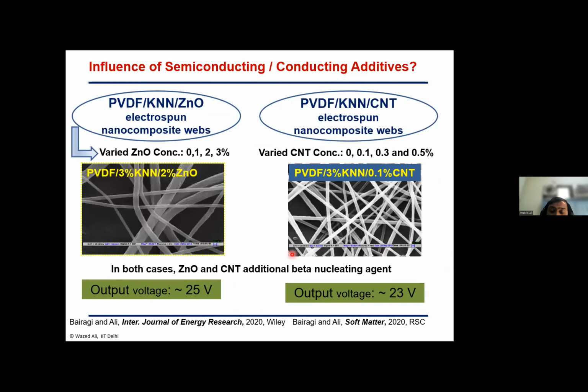And another concept has also been conceptualized over here. For example, if there is a charge which is going to be produced in the structure, that charge has to flow, right? Flow on the surface, so that by application of some electrode on the top and bottom, we can harvest the charge. So if we include some kind of semiconducting material or maybe some kind of conducting material within the fiber structure, along with PVDF, KNN, and for example, CNT, we have used as conducting filler, and also zinc oxide as a semiconducting filler. And by the way, zinc oxide is also piezoelectric in nature. And because zinc oxide is semiconducting as well as piezoelectric in nature, the output voltage is further higher, 25 volts.